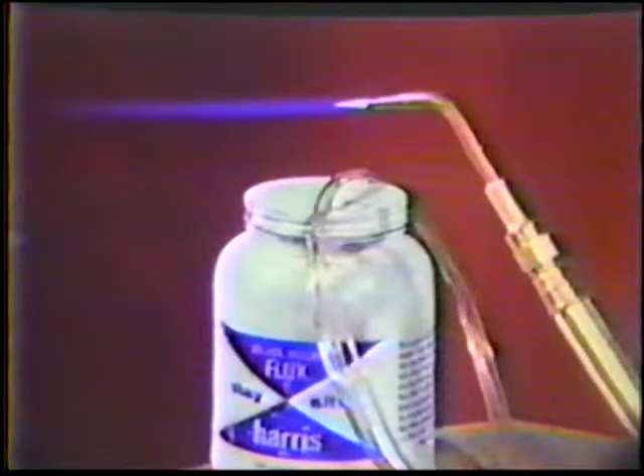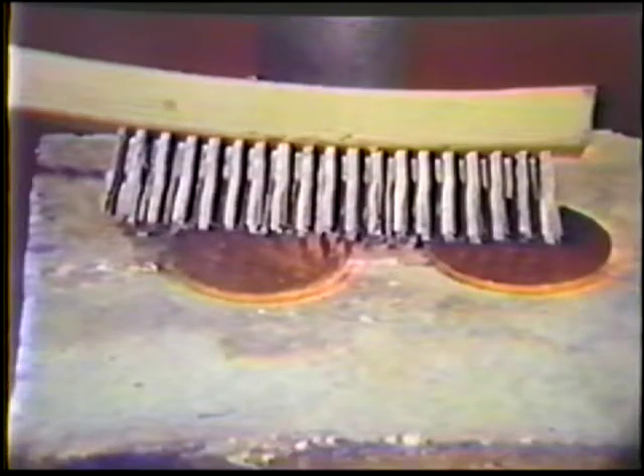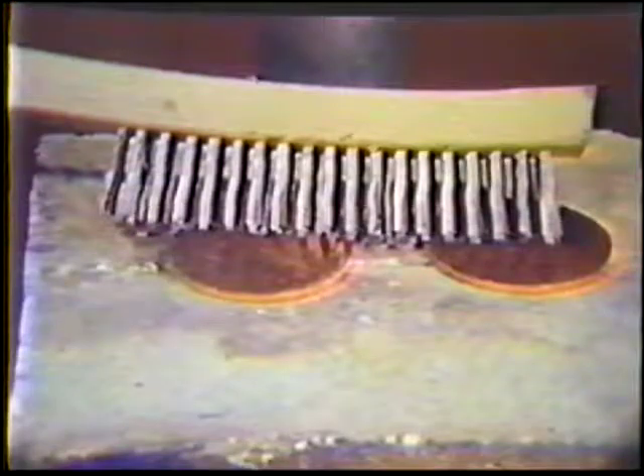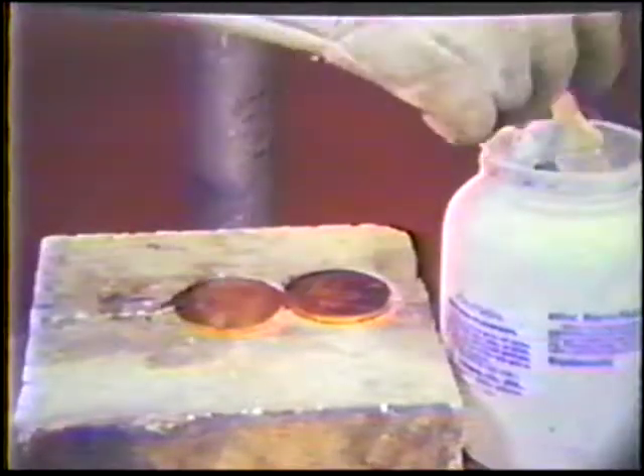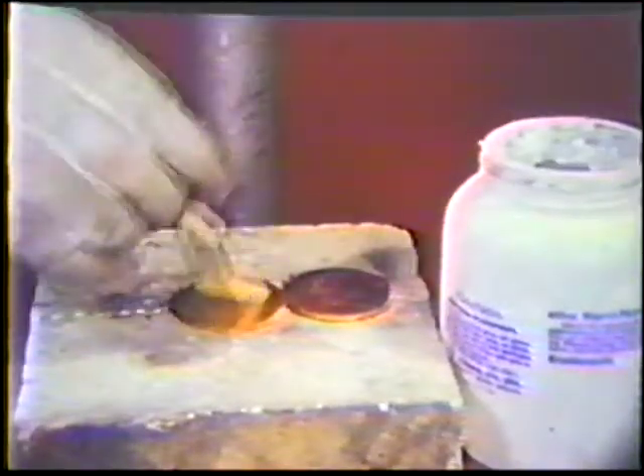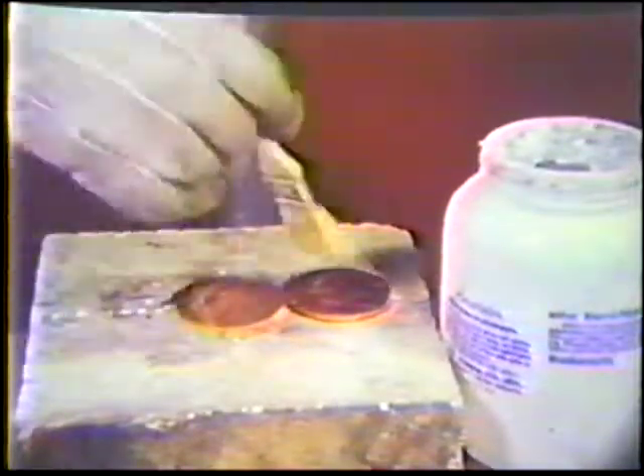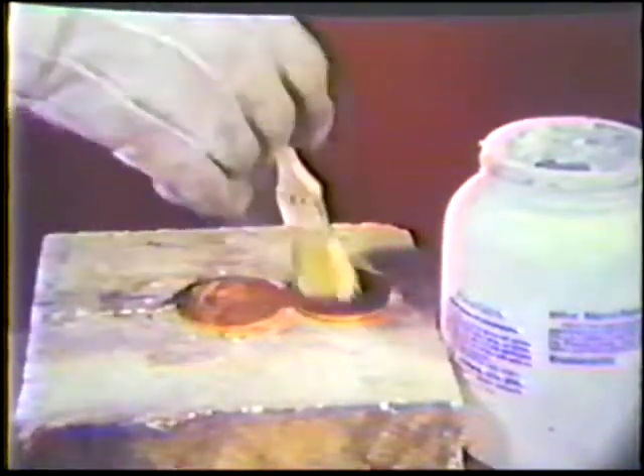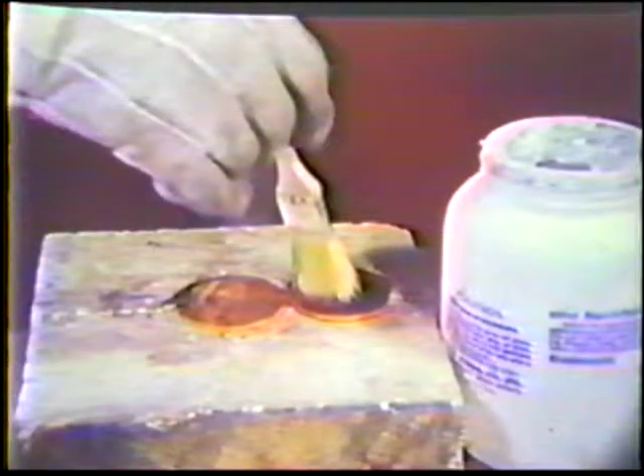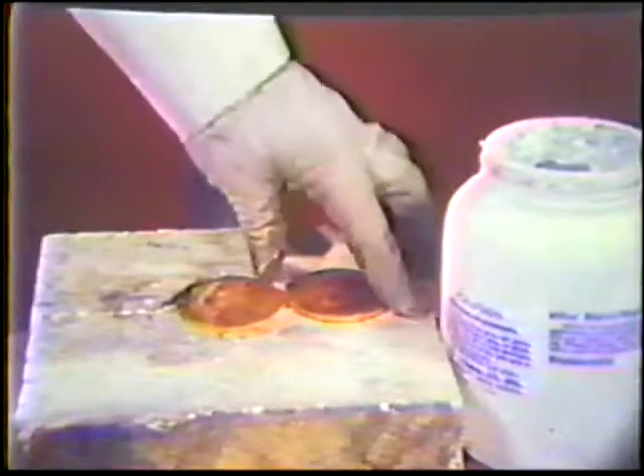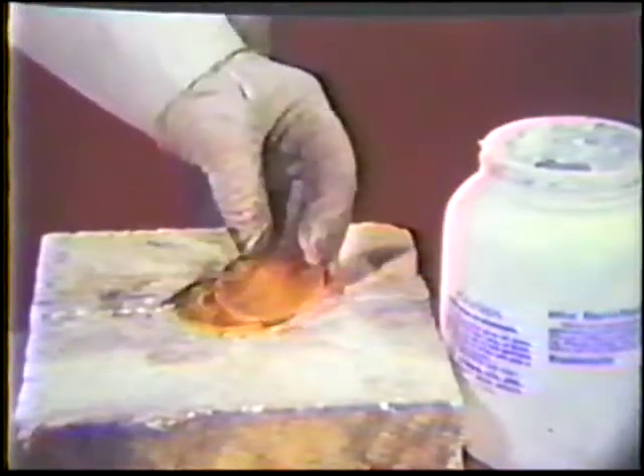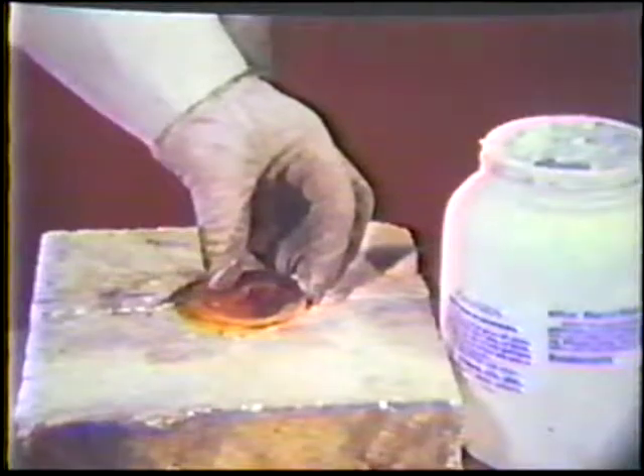To prepare the workpiece, first clean the mating surfaces of 2 copper plates. Apply flux to both surfaces. Do not apply too much, or the filler will flow to the cleanest area, and overfluxing can cause overbrazing. Then place the pieces together to form the lap joint.